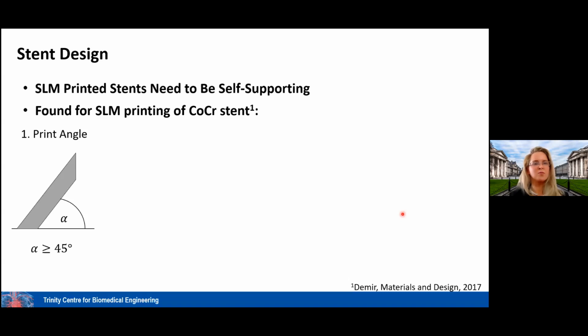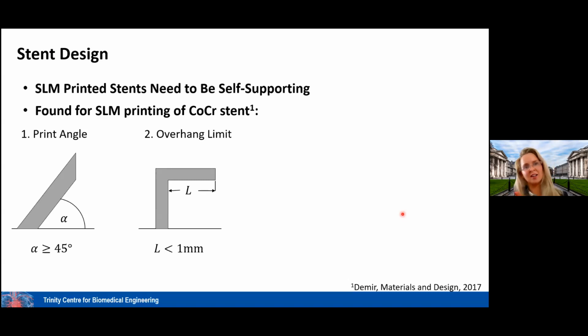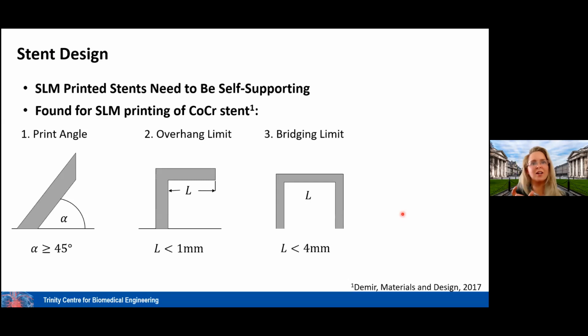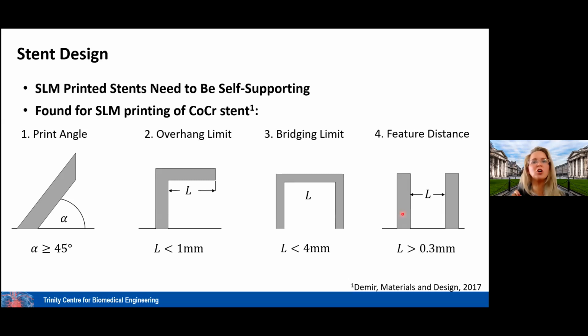And this is from Demir et al. They identified that we really need to have angles greater than or equal to 45 degrees for it to be fully supported. Any less than that, it's essentially going to collapse on itself. You have an overhang limit. You can overhang a little bit, but only by about 1 millimeter. And if you support on the other side, you can go a little bit wider, but you need to keep it less than 4 millimeters if you're bridging from one side to another. And when it comes to gaps, you do have to have gaps of large enough size, because otherwise you'll fuse things together. So the gap that you can have must be greater than 0.3 of a millimeter.